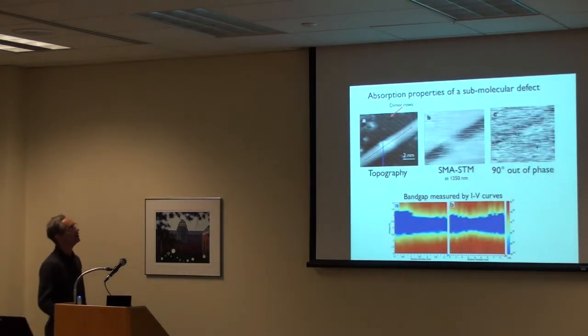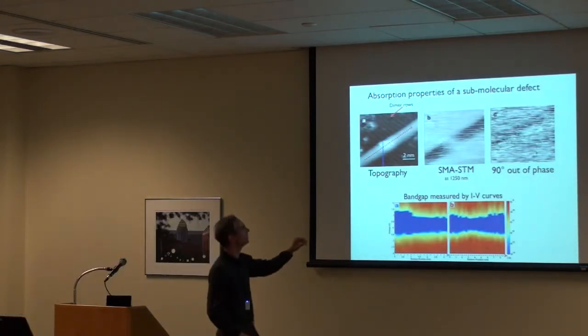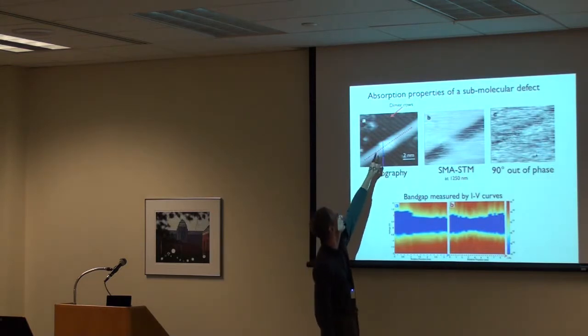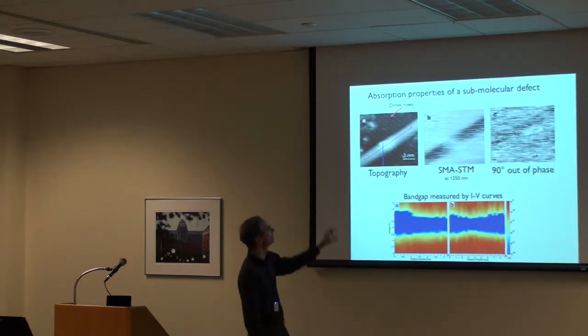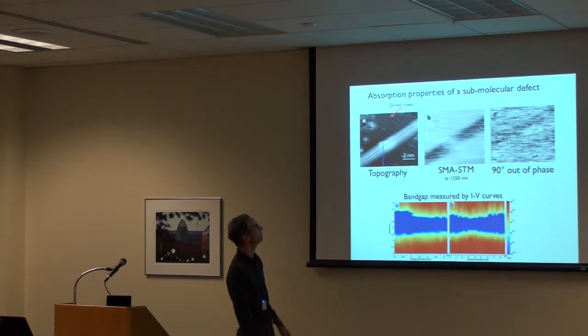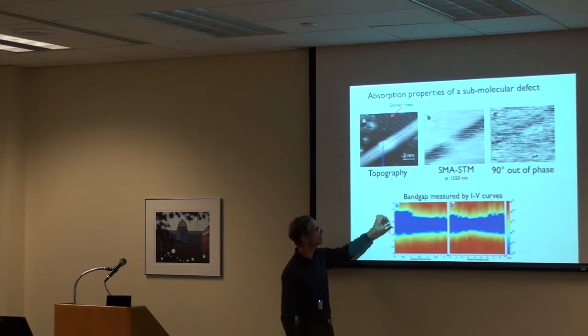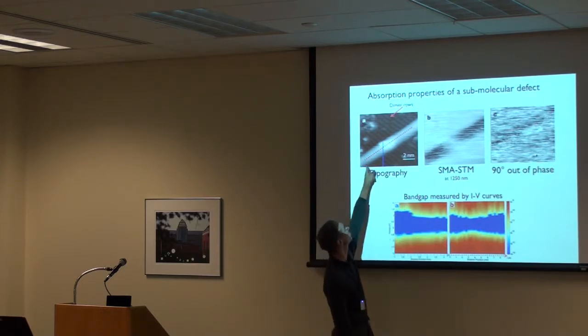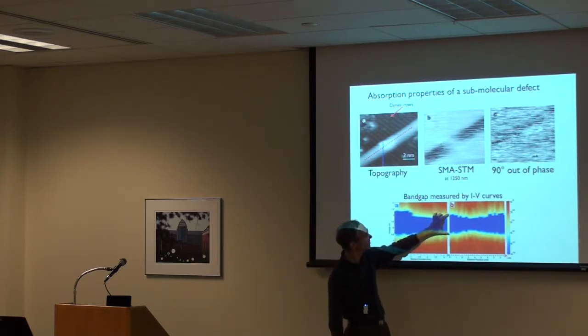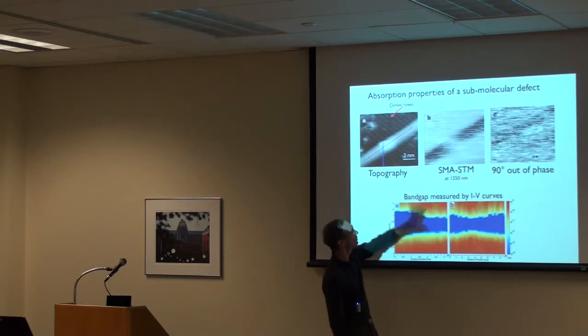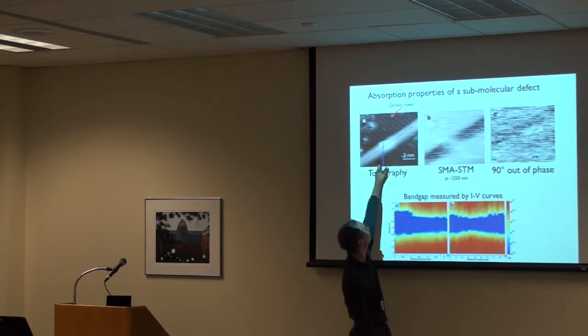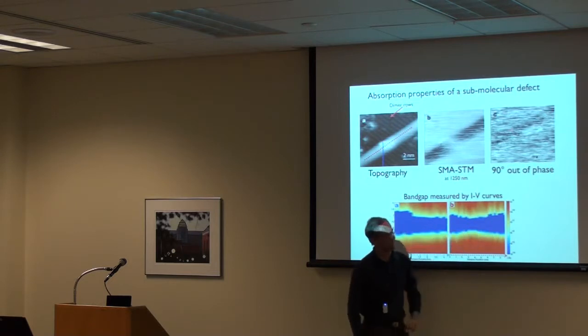Here's another example where we have a carbon nanotube that has been manipulated to have a defect. You can see it looks a little bit brighter than the rest of the tube sitting on the silicon surface. And sure enough, if we do an IV curve measurement along the axis of the nanotube, let's do the red curve over here, here's the band gap of the carbon nanotube out here. Then it shrinks when we get to the defect, and then the band gap increases again.